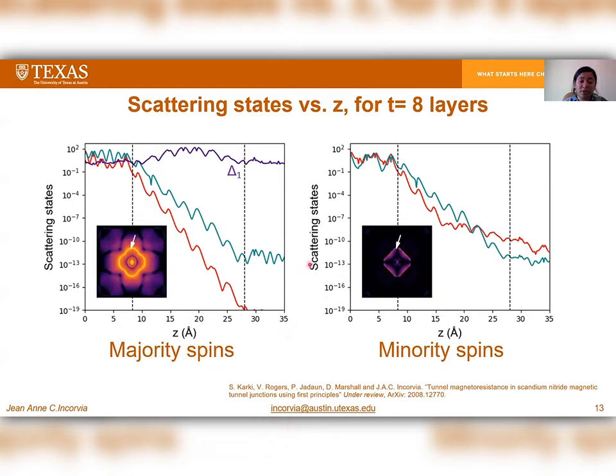Similarly, this is one for 8 layers at a different k point where we have higher transmission. We see that the major transmission is due to delta 1 at this point, which gets filtered out on the minority spin. Similar to the previous slide, this again validates our point that scandium nitride is an efficient spin filter.